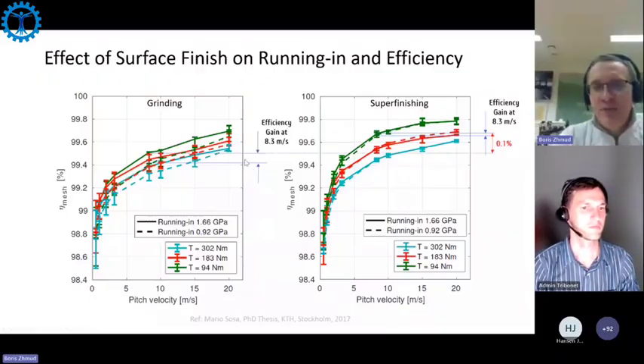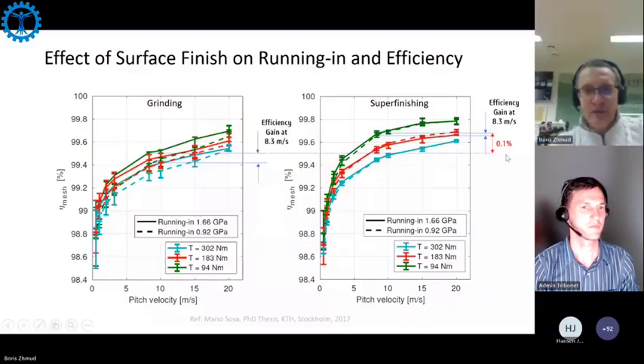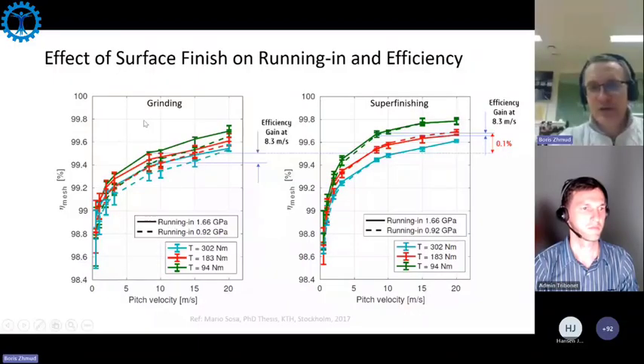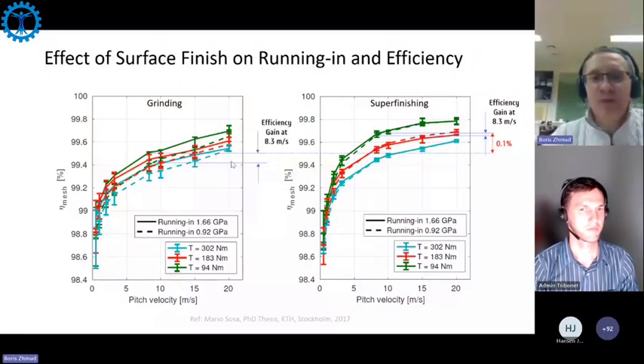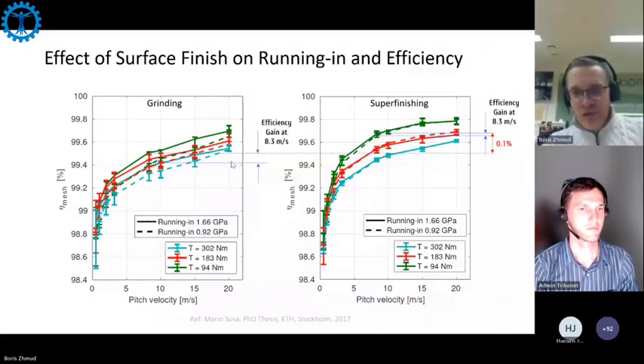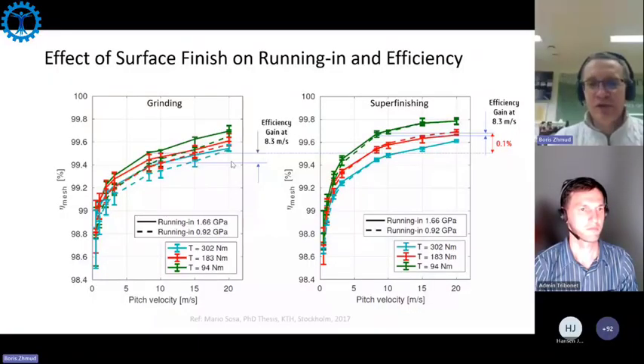It's also important to keep in mind the overall difference in efficiency after running in. For example, I take here the efficiency at 8.3 meters per second. You can see that efficiency after running in is always higher for super finished gears than for ground gears. So you can talk about a positive effect of super finishing on the running in process, which is remarkable for many reasons. You generate less particulate matter and less debris in the lubricant, so the lubricant stays longer in good condition, but you also have an efficiency improvement for the lifetime of the component.